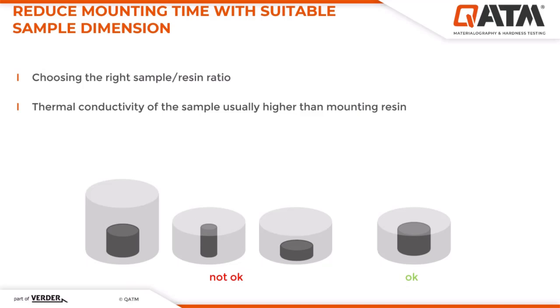The heating and cooling times in hot mounting are limited by the low thermal conductivity of the mounting material. Usually, the resin has a much lower thermal conductivity than the sample itself. To reduce the process times, the heat path through the resin should be kept as short as possible and the highest possible thermal conductivity to the sample should be ensured. For metallic samples, times can be significantly shortened by reducing the amount of mounting material, choosing the smallest possible mounting diameter, using suitable sample dimensions, and maximizing the contact area with the press cylinder.